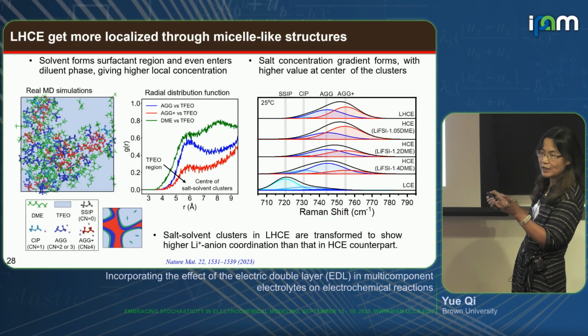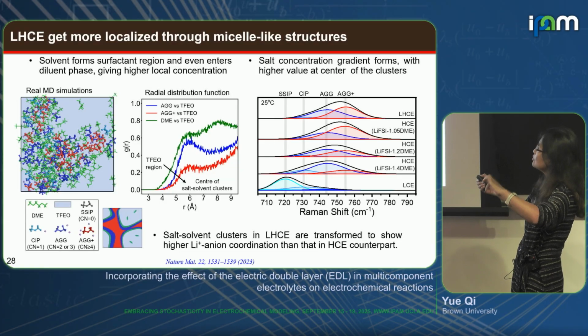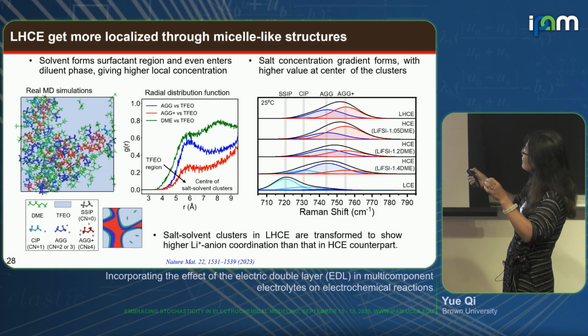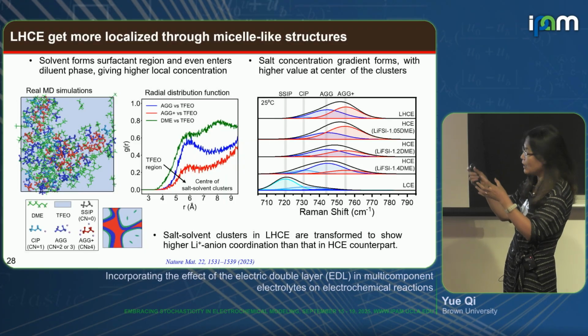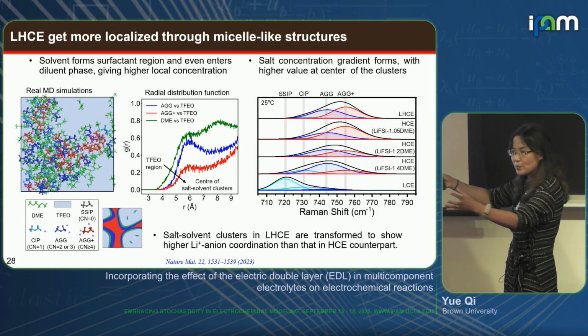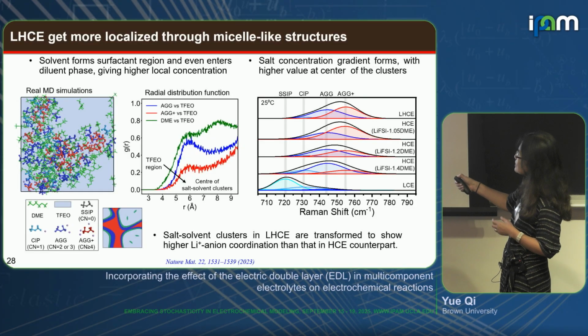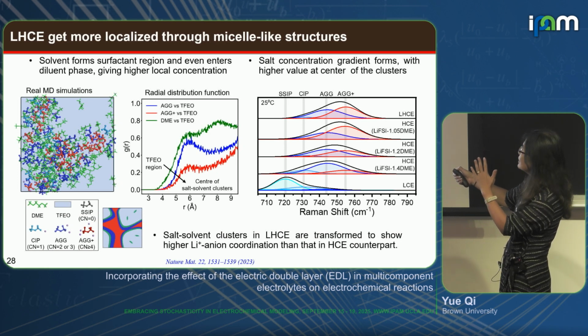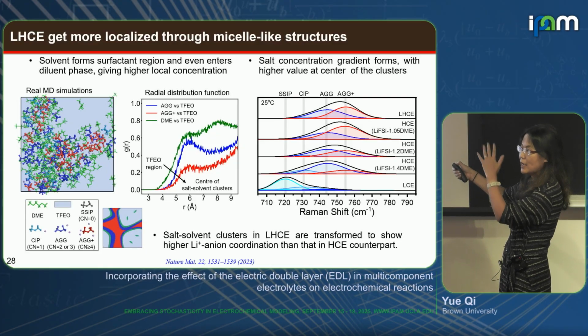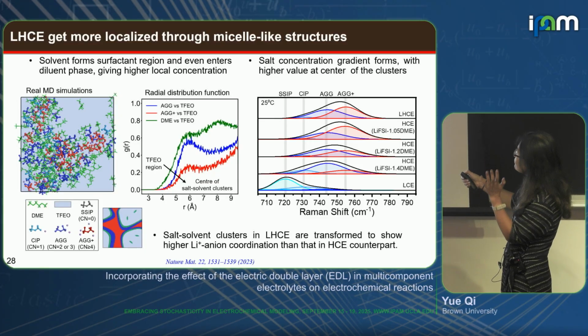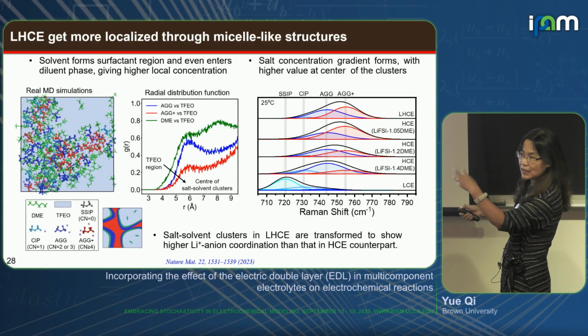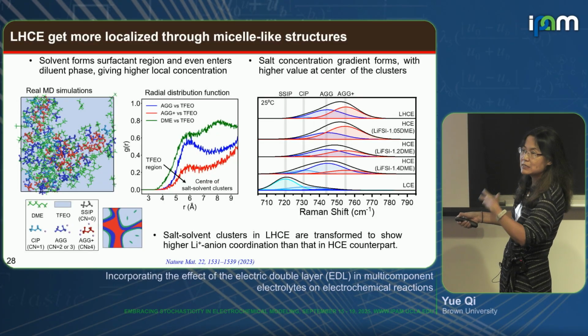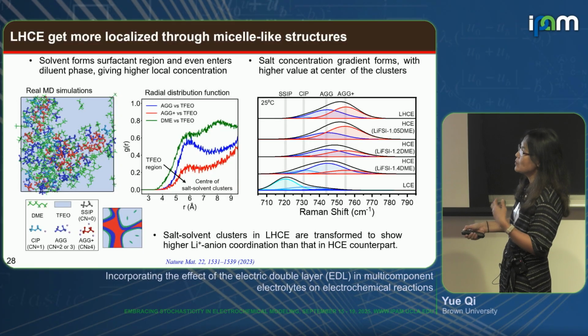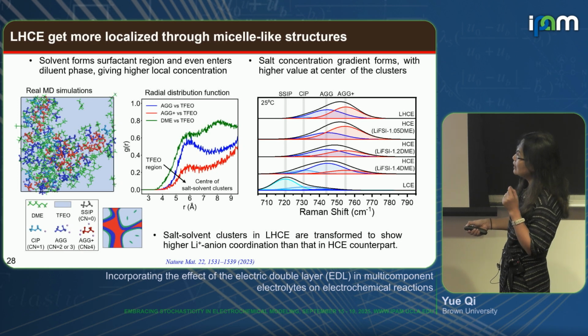If we make a high concentration electrolyte, and then pour this diluent into it to make the so-called localized high concentration electrolyte, and the salt-solvent cluster from the parent high concentration electrolyte simply dispersed, we should not see any changes in this peak. And this Raman peak moving toward the right means there are more salt aggregates, right? One thing that contributes to this is that the solvent molecules eventually have some percentage in the diluent. So we leave less solvent in this cluster to solvate the salt, and we end up with higher salt concentration. And that's characterized by all these pairs that Nidhi talked about: isolated pairs, aggregates plus.